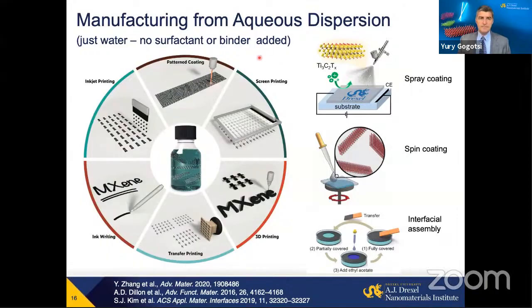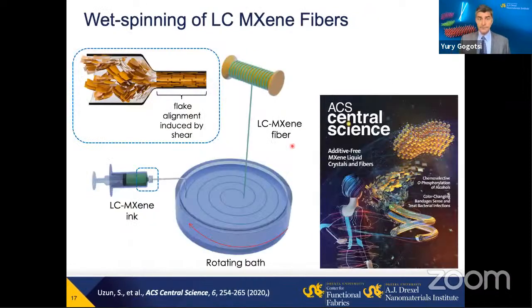So if we do, for example, inkjet printing, spray coating, or spin coating as a technique, unlike say metal nanowires or something else, we don't need surfactant. We don't need to burn binder and surfactant after producing the film. We just get natural adhesion between those layers.